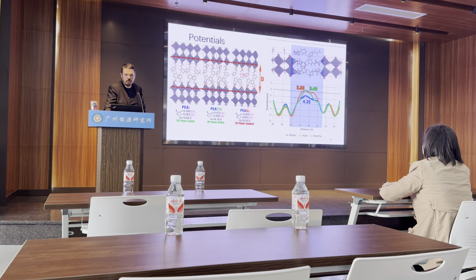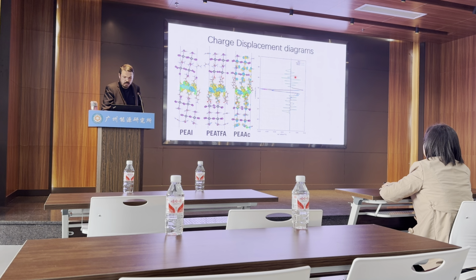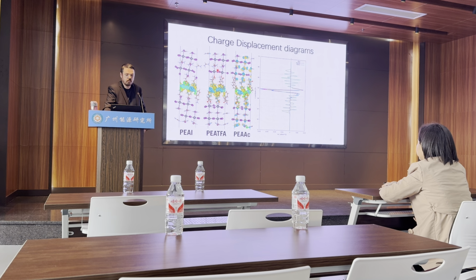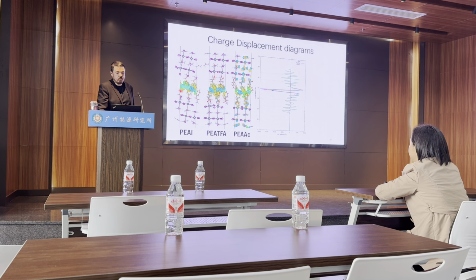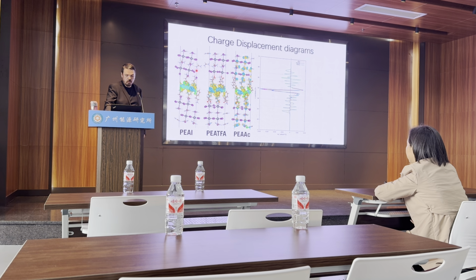The other thing to think about is what's different between the iodine-based one and the acetic-based one. You can see that the potential in the middle here actually decreases, and I'll show you in the next slide what that means. So basically, in this area between the passivants, when we make a 2D phase, we have passivant on one side, passivant on the other side, and the passivants meet. And when the passivants meet, we get a band of negative charge. So that's where holes will probably be attracted.